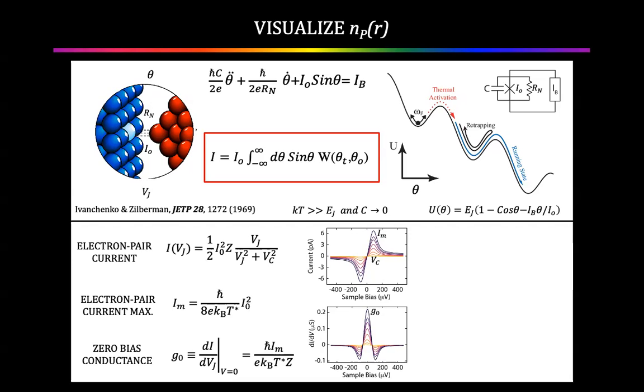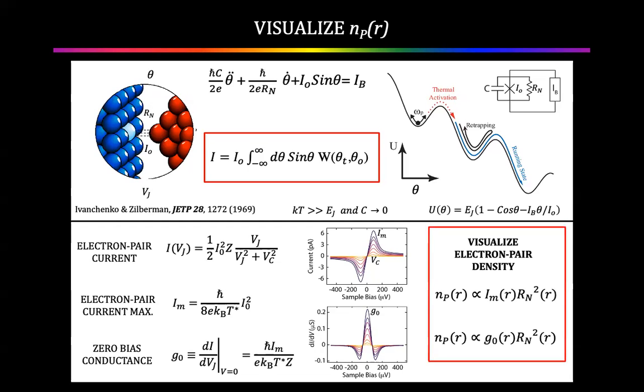So even though you can't fix the phase across this Josephson junction, you can still measure what's the critical current squared by measuring what's the maximum in the pair current. That's the working hypothesis. So now we would like to measure, image the electron pair, condensed electron pair density by measuring the maximum in the pair current at finite voltage and keep the normal junction fixed or deal with it by experiment.